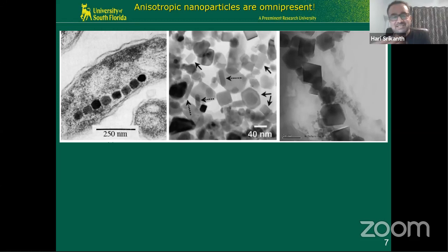Okay, so what makes these 3 TEM images interesting is the source where these nanoparticles come from. Let's start with the left. It turns out, and some of you might guess what it is, these are magnetite nanoparticles in bacteria. There are these bacteria which are magnetotactic bacteria. They actually produce nanocrystals of magnetite, and they chain them up using dipolar coupling. They chain them up and essentially form these short chains. And the reason they're doing it is exactly what the Chinese did when they discovered the compass. Basically, they discovered what is called lodestone magnetite, and they found that iron or magnetic materials can respond to it, and they used it for navigation. So these bacteria are essentially making tiny compasses, and they're making this to search for a source of food. That's what they're doing, right?